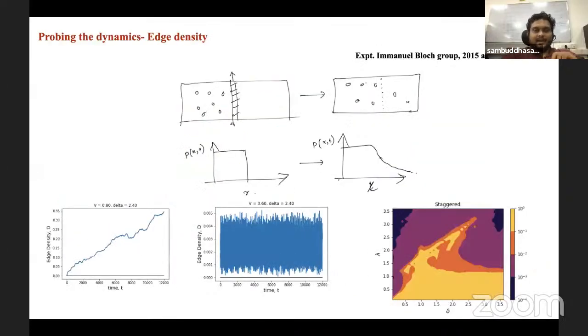So then we finally come to another dynamical probe, which was done in an experiment in Immanuel Bloch's group. The idea is very simple. If you have a box of gas and you confine all the gas particles in the left half, and then you suddenly remove the partition which confines all the particles on the left half, the gas will spread into the right half. How much it spreads as a function of time will tell you how localized or how delocalized it is, and that can be experimentally measured in these optical lattice systems.